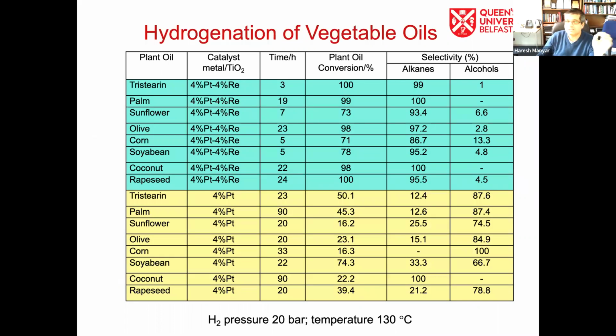We tried this on a range of different vegetable oils like palm, sunflower oil, olive oil, corn oil, soybean oil, coconut oil, rapeseed oil, all of them. We could achieve very high selectivities, high 90s, 95 to 100% selectivities to alkanes, or we could have very high selectivities in the range of 80 to 90% towards the alcohols directly from the oils. So it saves a lot of